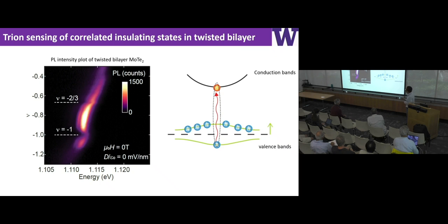The intensity drops. The reason is, as I mentioned at the beginning, a trion is an exciton bound to a free carrier. But in a system where a correlated state forms, meaning a gap state forms, then the Fermi surface is gapped. The number of free carriers to form trions is reduced. So you can think of the number of trions also being reduced. Therefore, the luminescence from the trion will also be reduced. So what we do is look for the reduction of the trion luminescence population. This is a signature of the formation of a gapped state.